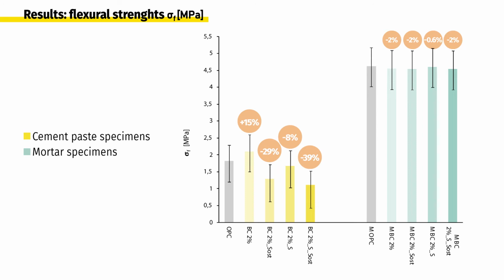In the case of mortar, it is possible to appreciate how the use of 2% of biochar represents a slight loss of resistance of just 2%. However, when the biochar is fully mixed in the cement powder, the flexural strength drops less than 1%. In the cases where biochar was used as a substitute for cement, there was a slight loss of resistance of only 2%, regardless of whether the biochar was mixed with water or cement powder previously.